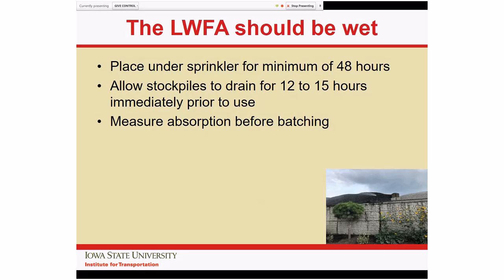The one negative of this is we need an extra bin, and we have to ensure that the aggregate going into the batch plant is pretty close to saturation and yet not too wet. The way New York DOT set it up, their specification states the aggregate should be run under a sprinkler for about 48 hours, and then you allow it to drain for 12 to 15 hours. Now, we had occasion last year in Iowa where we were doing this, and it was raining solidly. In the end, the decision was that the draining was less critical.